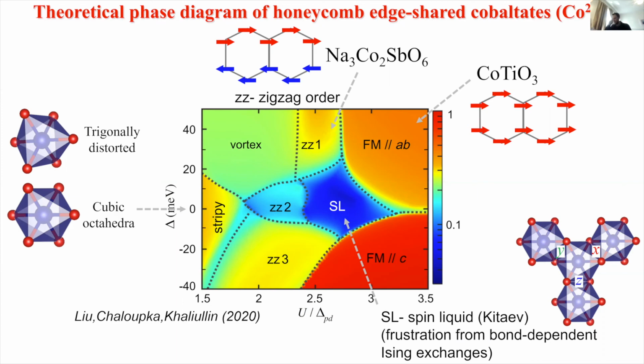And then, as compared to the 5D or 4D compounds, another competing interaction is just direct exchange, right? I guess that's weaker in cobalt because the 3D orbitals are smaller. That's right. That's what Chaloupka, Khaliullin proposes in this paper here, that the direct exchange is weaker. And the thing that's different here is that you have EG electrons. The EG electrons tend to have a Heisenberg interaction that's antiferromagnetic, and T2G that's ferromagnetic. So they tend to cancel each other and help the Kitaev. So this EG part is missing from the 4D and 5D. So potentially in 3D, having a slightly different spin orbital ground state could help get closer to this limit.